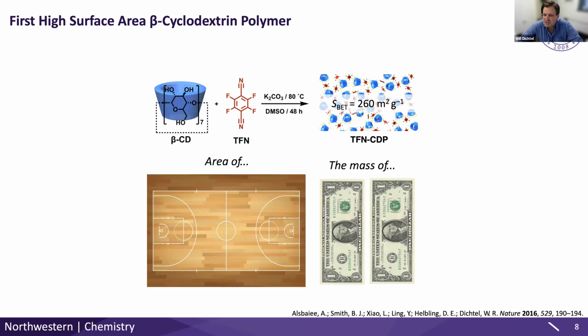Part of the secret, as I said, was the surface area. We measure surface area in units called meters squared per gram. To help wrap your mind around that concept, this material has a surface area of 260 meters squared per gram. That's approximately the area of an NBA basketball court if you could somehow unravel the surfaces of this material and lay them out flat. An amount of material that weighs as much as two $1 bills, so about 2 grams, would cover the surface of a basketball court. But in our hands, it's just a powder that fits into a very, very small glass vial. And so that surface area provides access to these cups so that they can do their jobs very quickly.